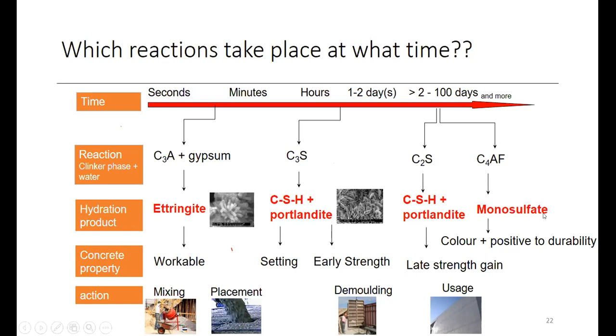The C4AF usually produces a reaction similar to C3A with gypsum. It's also happening like a monosulfate. Initially, within a few seconds or minutes, the reactions will happen, and it will take a few hours to start the C3S reaction and a few days to start the C2S and other reactions.